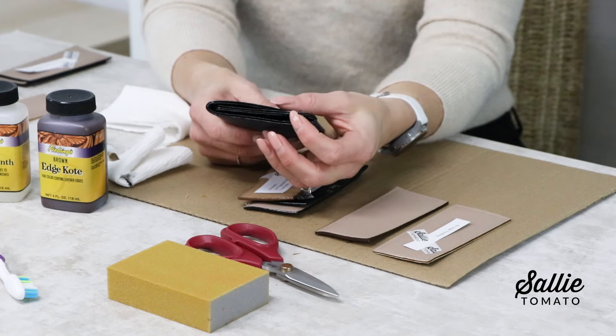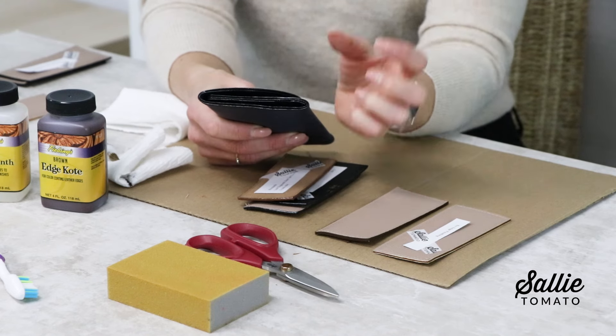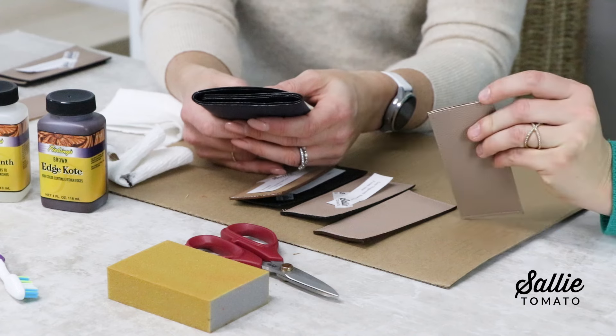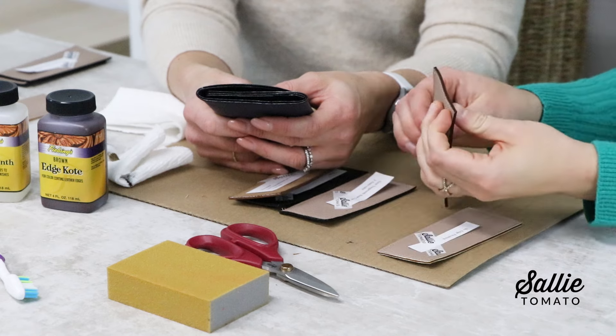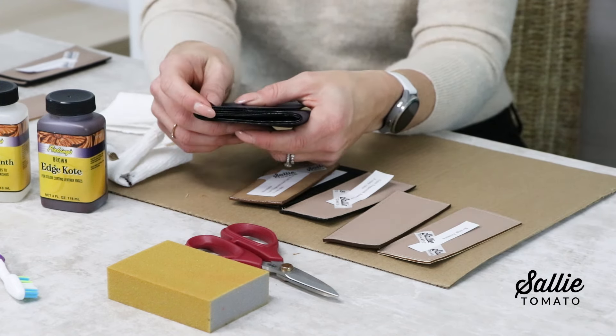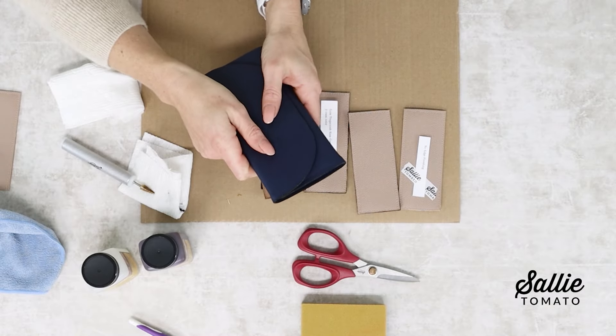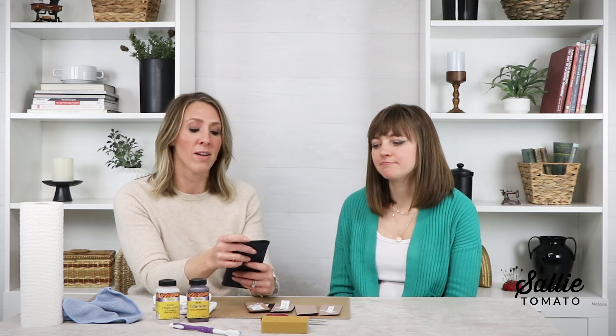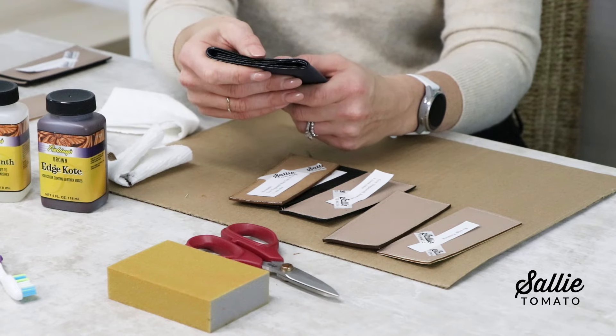We also tried it on our laser cut Lucky Penny kit. We wanted to test it on those laser cut edges because they will act differently than a natural cut edge. You can see it still gives a shiny, beautiful edge, but the edges don't mesh together like they do on our other materials. The Gum Tragacanth helps bond fibers along the edges to look like one seamless piece, but because those edges are burned when we cut the kits, it just doesn't gel quite the way we'd like even with three coats of Gum Tragacanth and three coats of color. So if you buy any of our laser cut kits and the finish doesn't look like the others, it's nothing you're doing wrong — it's just how those edges respond.